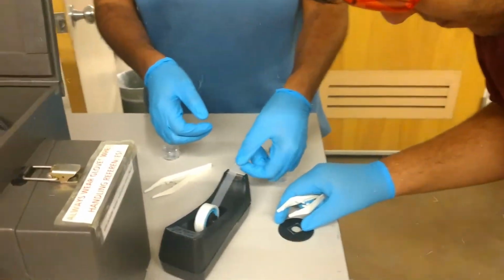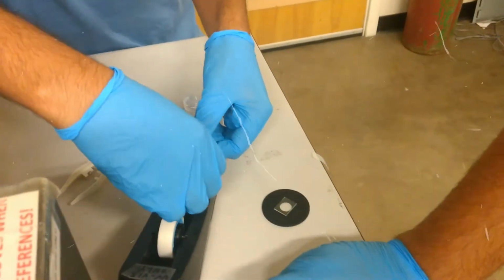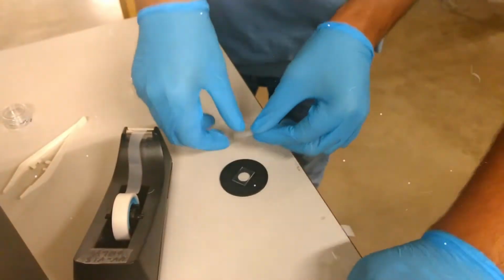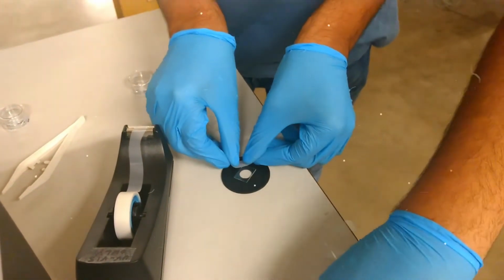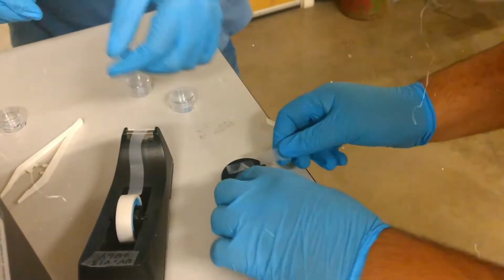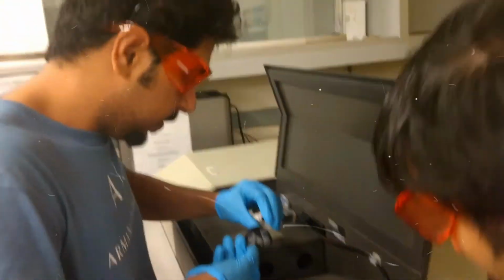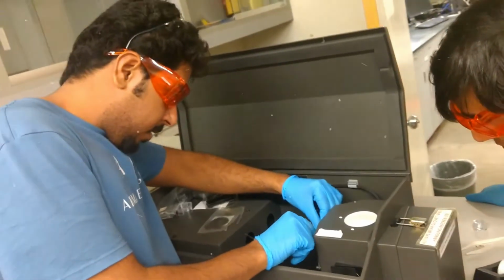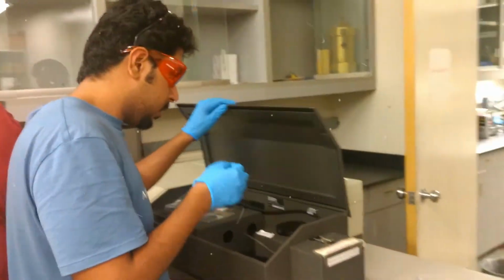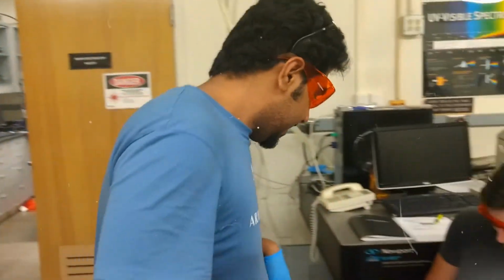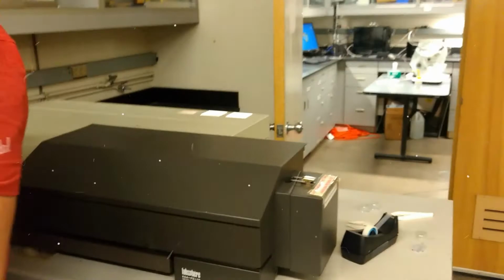After the spectrometer has been started, warmed up, and set up in the reflection configuration, a sample is secured on a non-transparent material, allowing no light to escape the chamber except to contact the sample. The sample is carefully placed inside the spectrometer, and then the cover is closed. Safety glasses must be worn while the spectrometer is actually in operation, as the UV spectrum is harmful to the eyes. During operation, the spectrometer starts at the red end of the visible spectrum and gradually shifts the wavelength toward the UV over the specified amount of time.